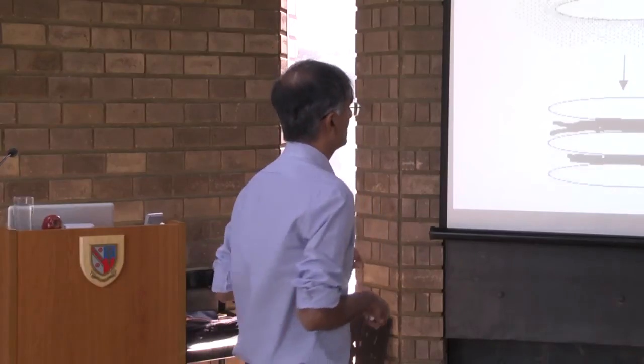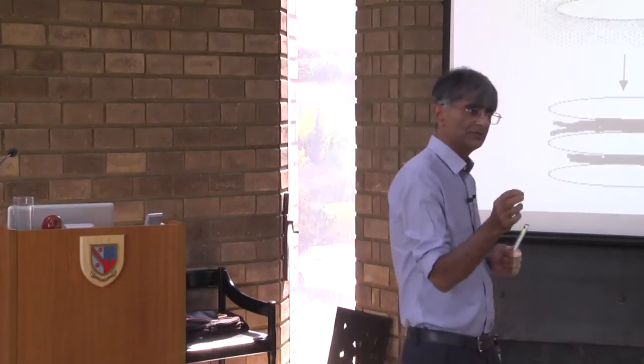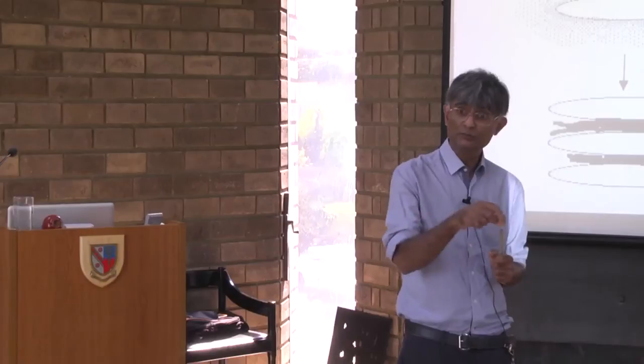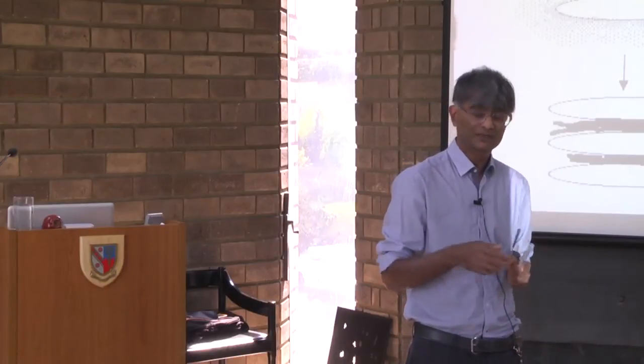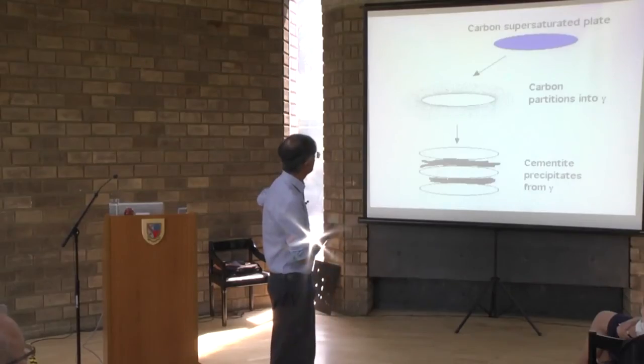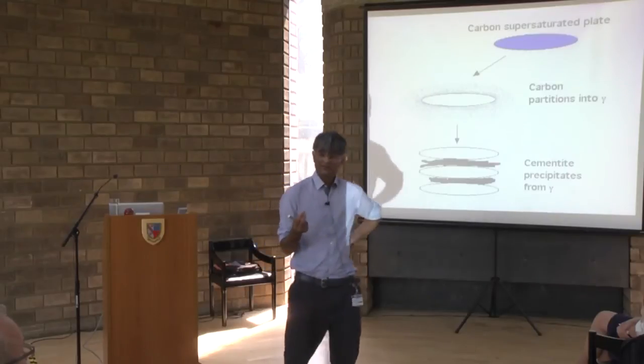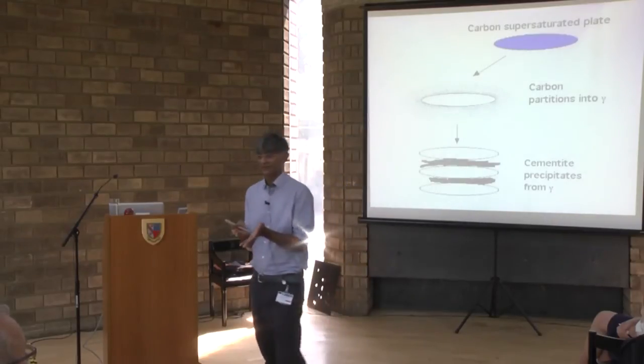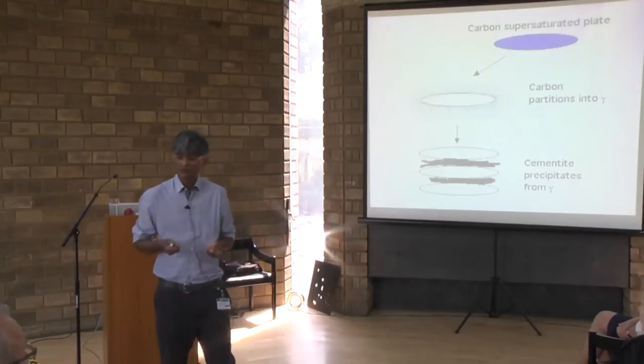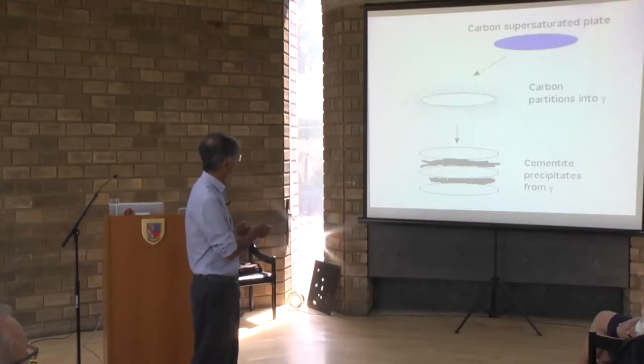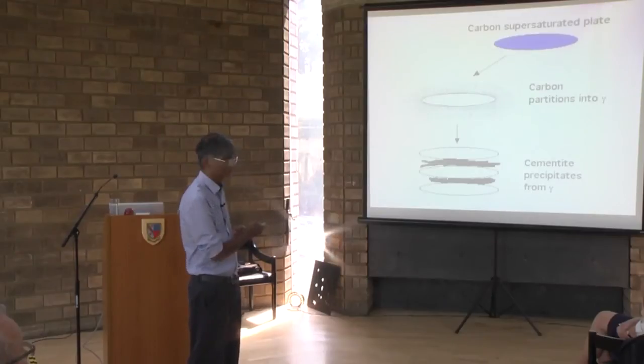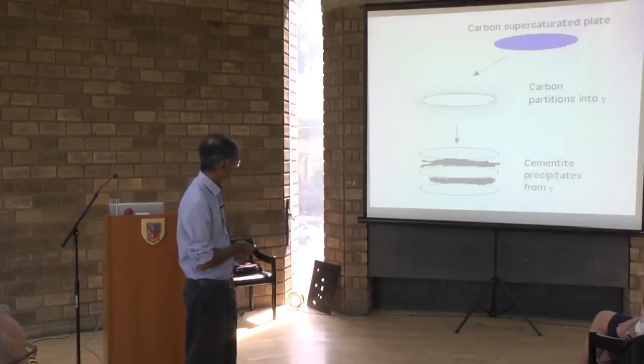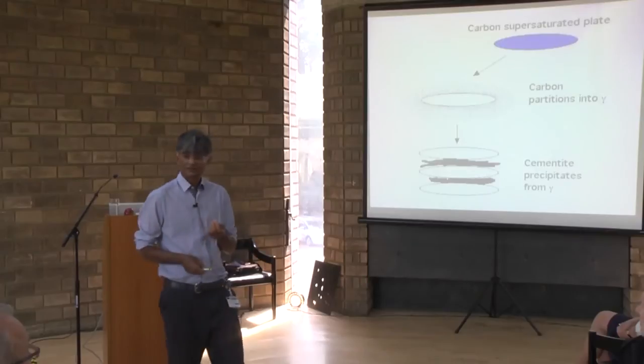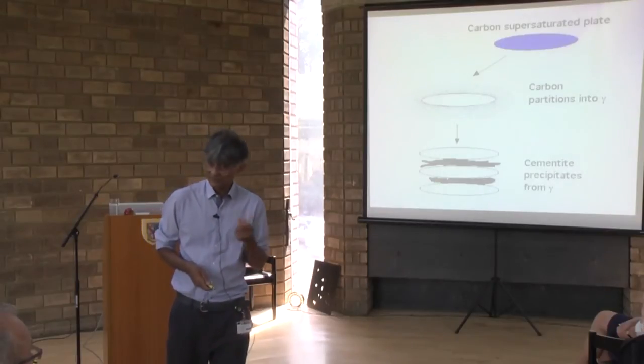However, carbon is a very small atom compared with iron, and it's able to move about much more rapidly than iron. So it doesn't like to be inside that body-centered cubic phase. It wants to get out and go into the parent phase. Within about a quarter of a second, the carbon escapes from here into the surrounding, and sometimes it precipitates as a brittle phase called cementite, which is an iron carbide.